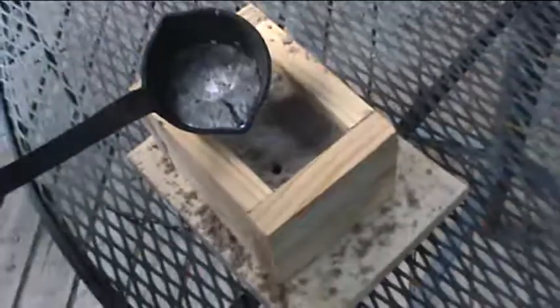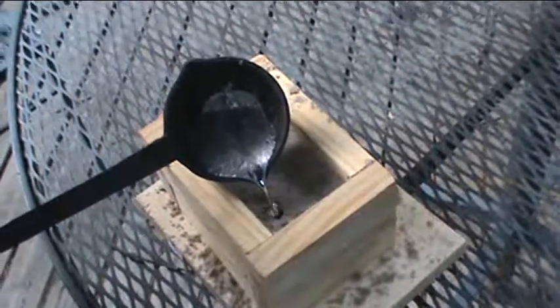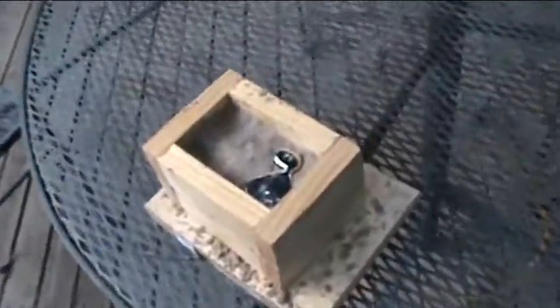When it's fully liquid, it's time to take it to our mold. We want to make sure this is close by. We don't want to walk around with molten metal. Just start pouring it into the sprue. Don't stop. Just pour quickly until it's completely full. Overfill it just a little bit. Now we'll just wait about five or ten minutes for it to solidify.